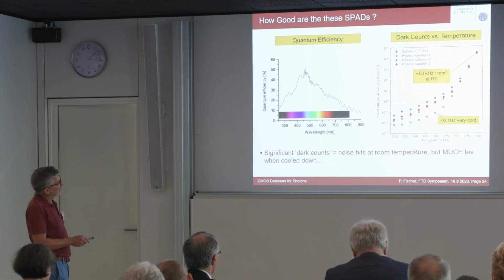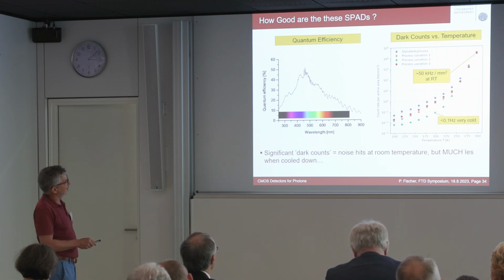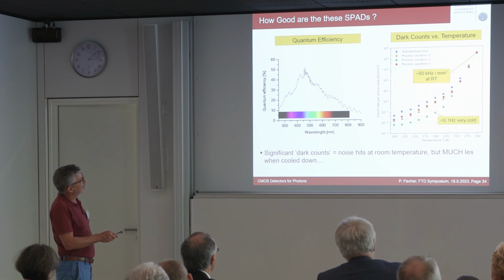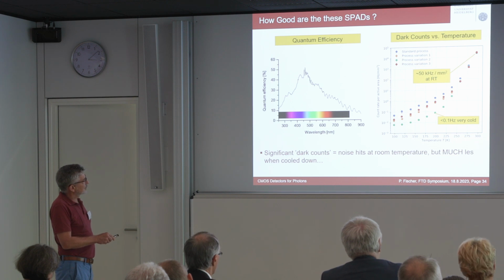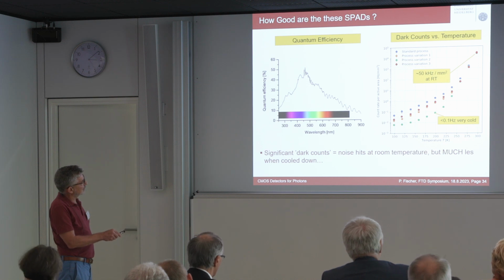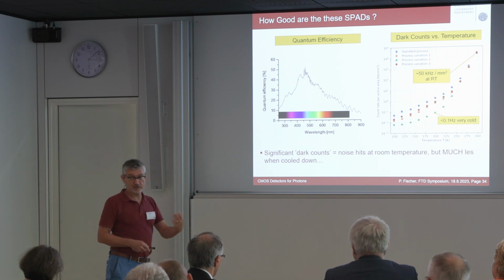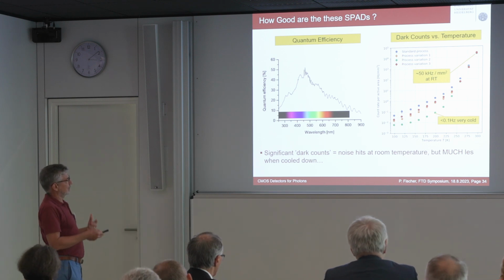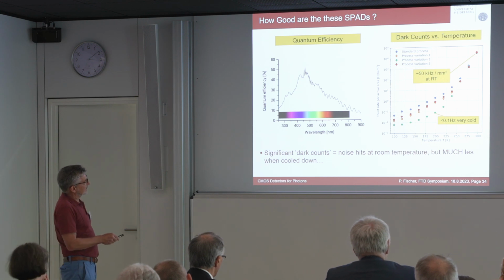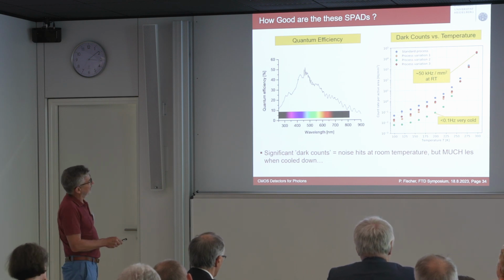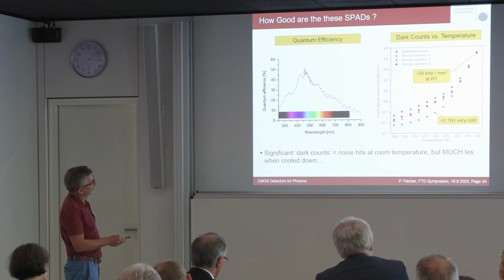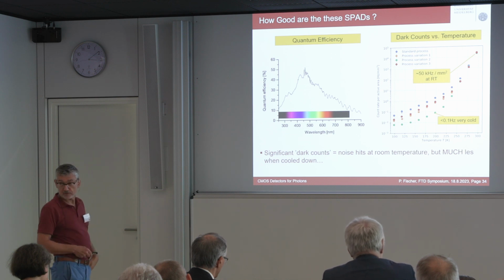And this was one result of an optimization process. You see several curves here. The original process we got from Fraunhofer is the blue process. It's not so good. And for the experts, there is a thermal contribution which is going down exponentially, and then there's a floor which comes from tunneling. And the tunneling depends on the field details. This tunneling effect you can in principle improve, and they changed some doping profiles in the devices, and they brought down the tunneling really a lot. So the tunneling is much better.